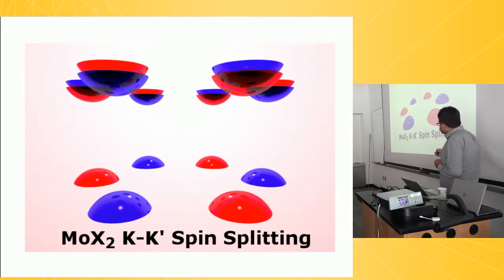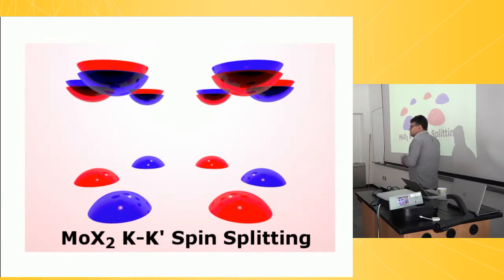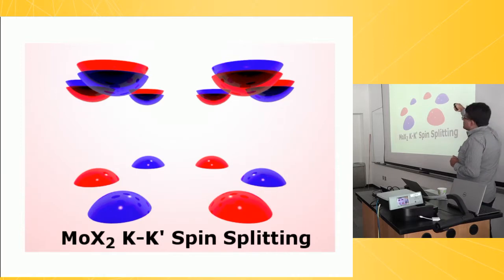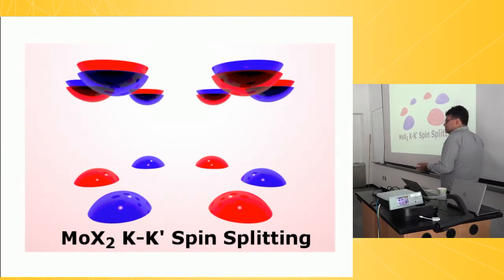Interestingly, in the tungsten, this is exactly reversed. So the blue guy is down below, the red guy is up above. And so in the tungsten, what you expect is as you cool down, you get trapped in this dark state, and you can no longer emit light. So you expect no photoluminescence at t equals 0.